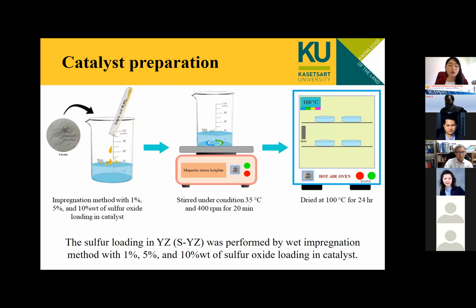Catalyst preparation. The conventional catalyst was Y zeolite. The sulfur loading in Y zeolite was performed by the wet impregnation method with 1, 5, and 10% by weight of sulfur loading in the catalyst. Firstly, 10 grams of Y zeolite and sulfuric acid were mixed in deionized water. Then the mixed catalyst was stirred under conditions of 35 Celsius and 400 revolutions per minute for 20 minutes.